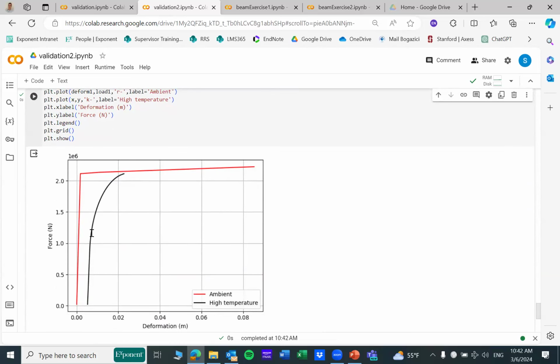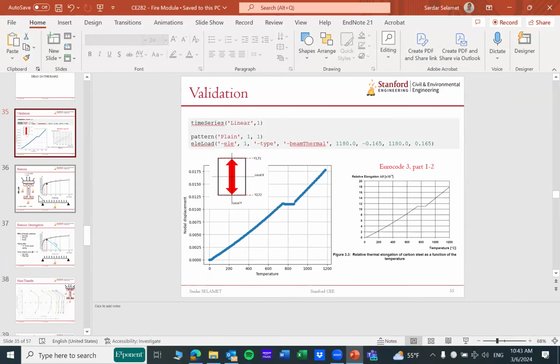First of all, you'll see that it actually stops converging at some point because it's highly ductile at this stage. Second of all, it shifts. There's a shift between those two, and that's accepted because the first one, we didn't apply any thermal elongation. The second one, we applied a thermal elongation. So it actually starts with some deformation, stress-free, but it is a deformation, and then it moves on. So you can see here that our material also behaves as we want it to behave. So these are the two validations. Any questions?